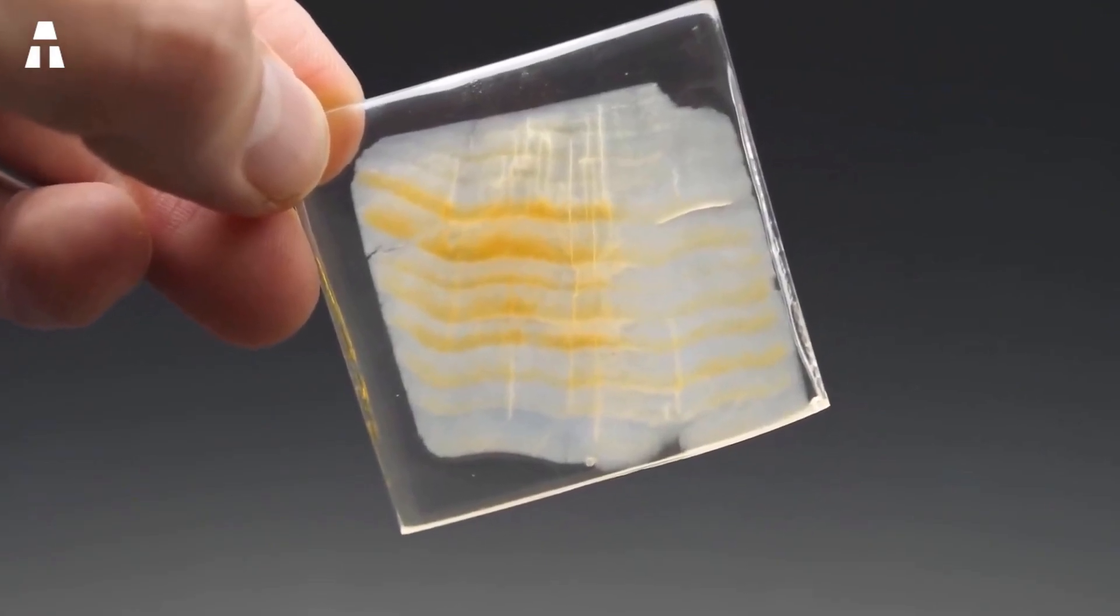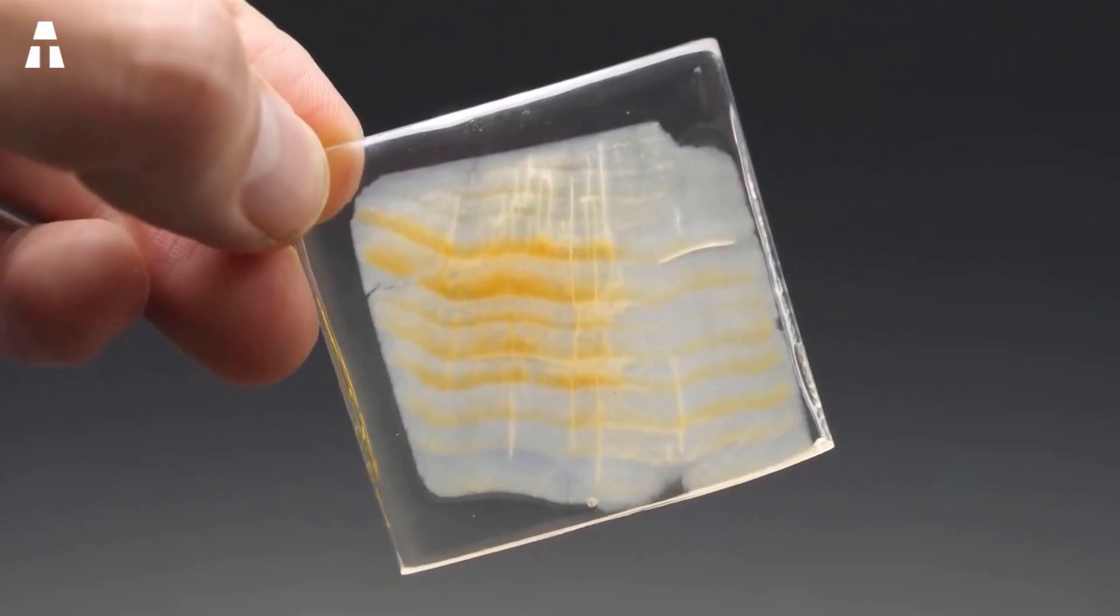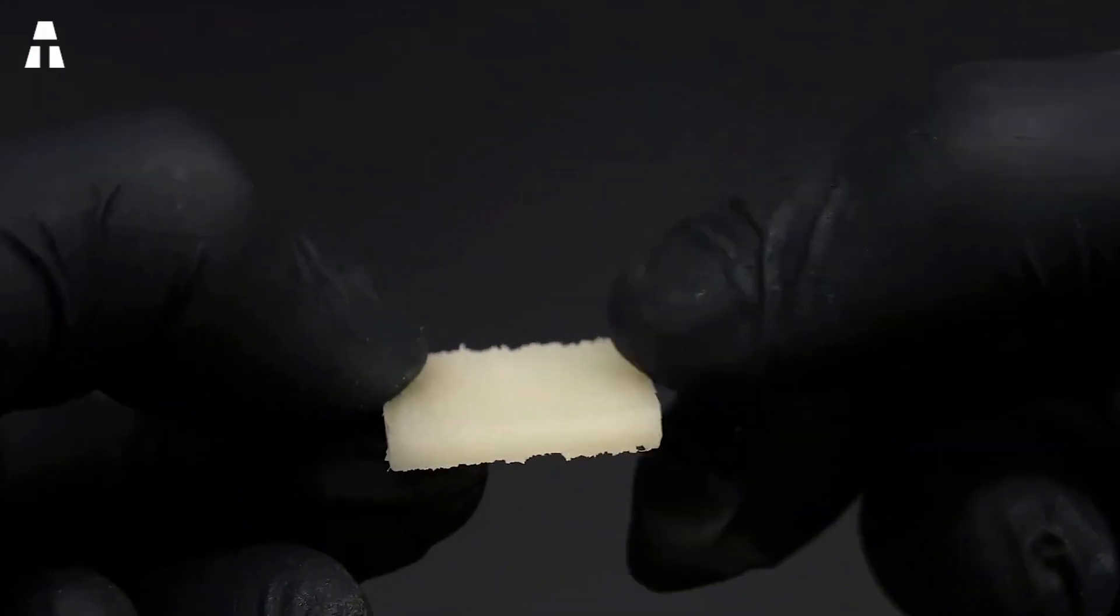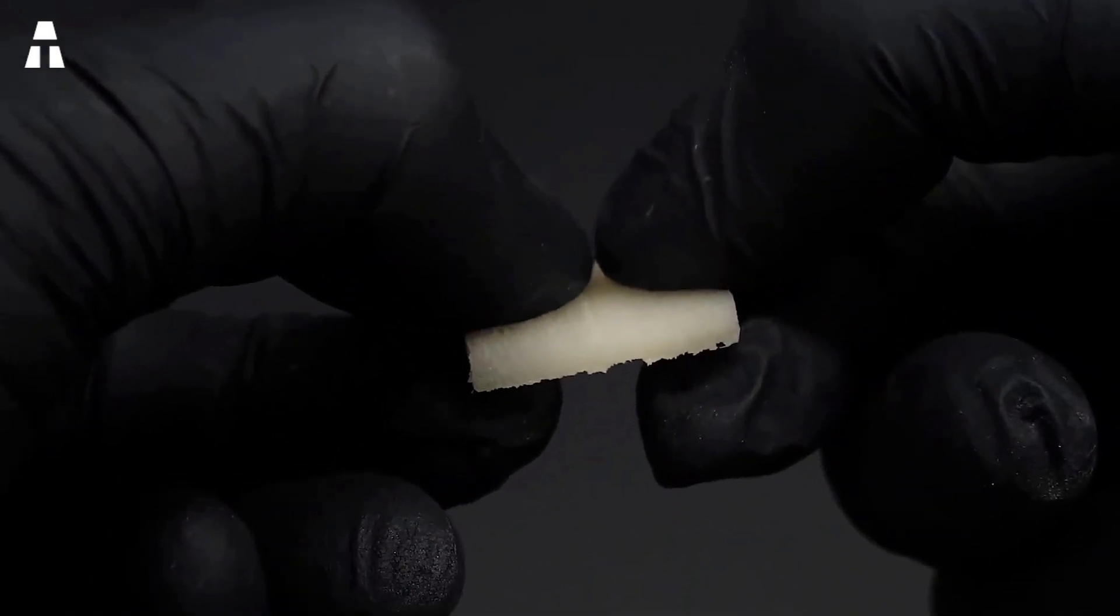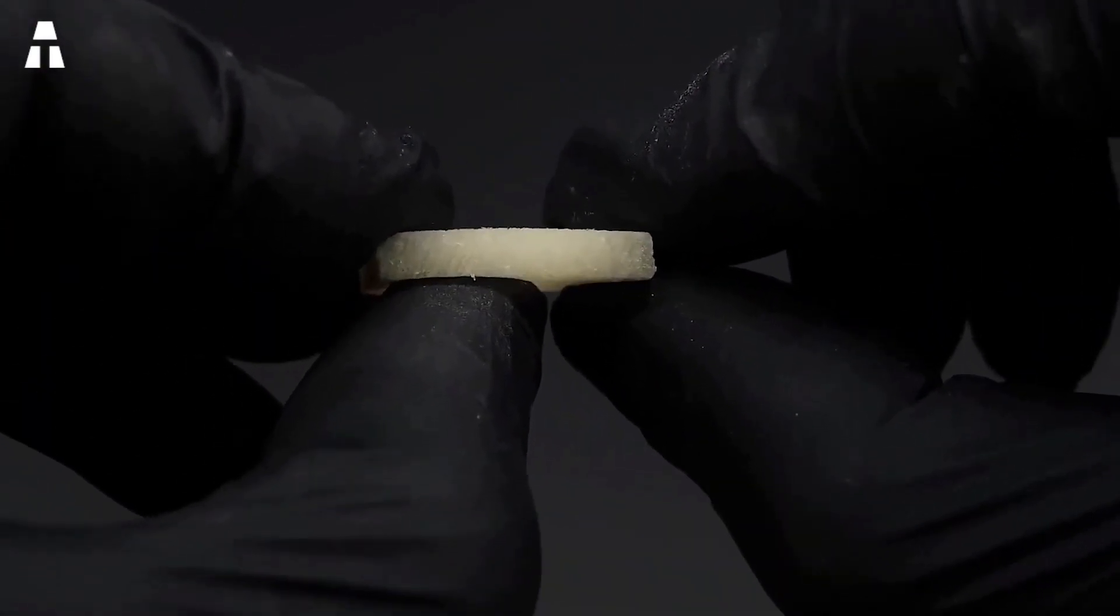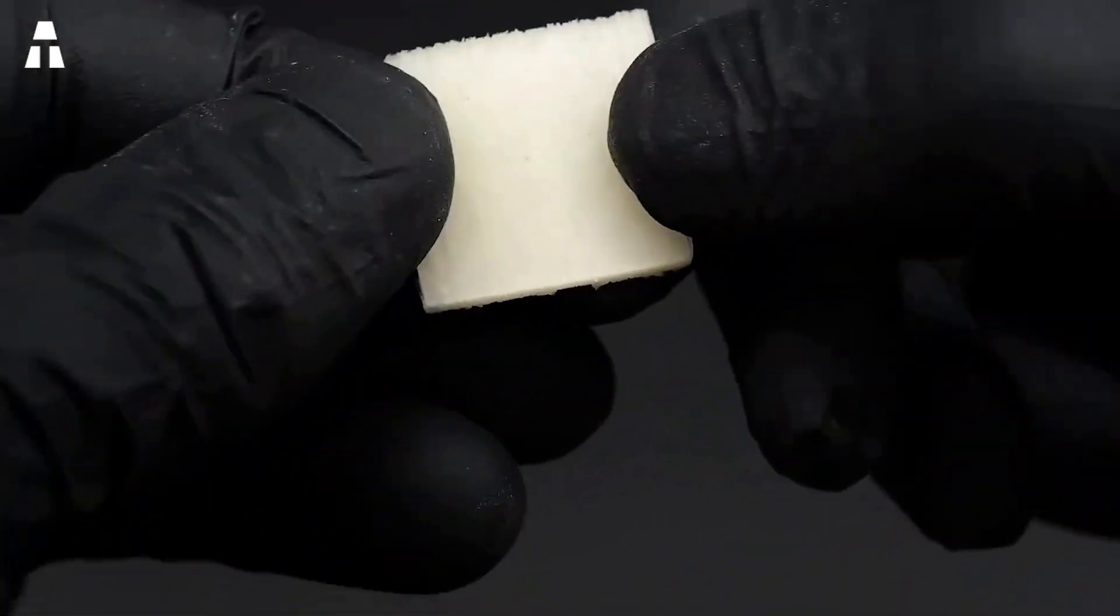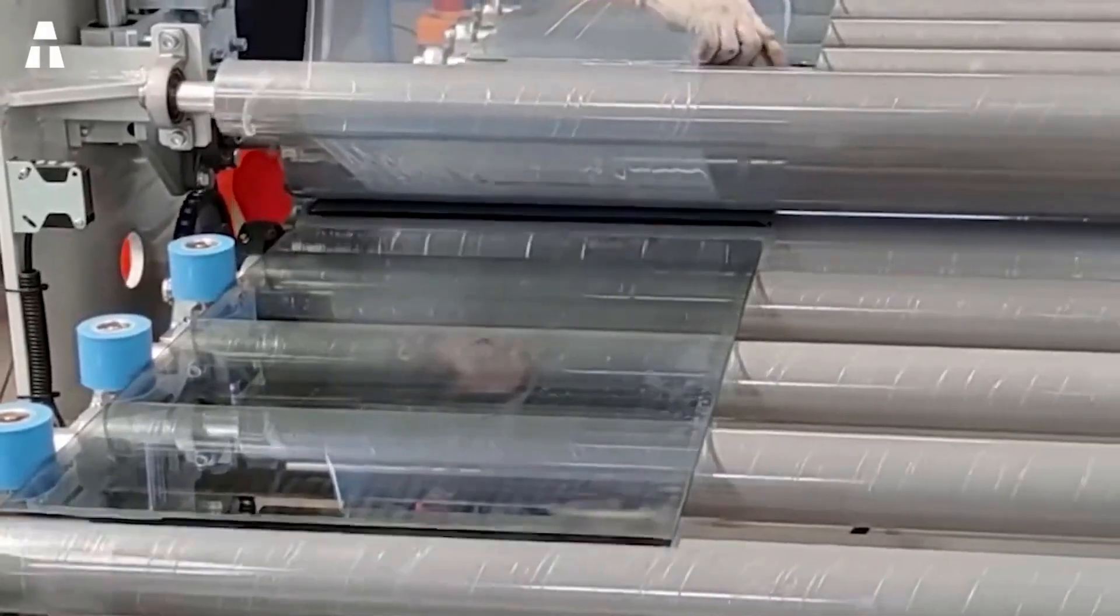At this stage, the boards have lost their opacity and are already almost transparent due to the oxidation. After soaking the wood in ethanol to remove dirt, the next step is to impregnate the wood with a tough, transparent epoxy resin designed for marine use. The resin then fills the spaces in the wood and hardens. The white wood then becomes transparent. The epoxy resin allows 90% of the light to pass through the wood.